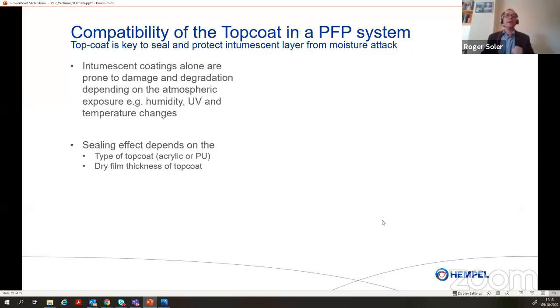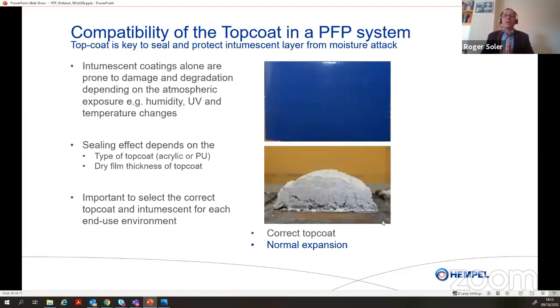So there are very demanding conditions during the life of the building, depending on the exposure, like humidity, ultraviolet rays, temperature changes, and it will depend on the type of top coat that we are using. It's important to select the right one so that they behave in the same way, for instance, with thermal expansion and contractions. Here I'm showing a picture of a sample of a system that has the same thermal expansion and behavior. So after the exposure, there are no cracks. And when we test them in fire, there is a normal expansion.